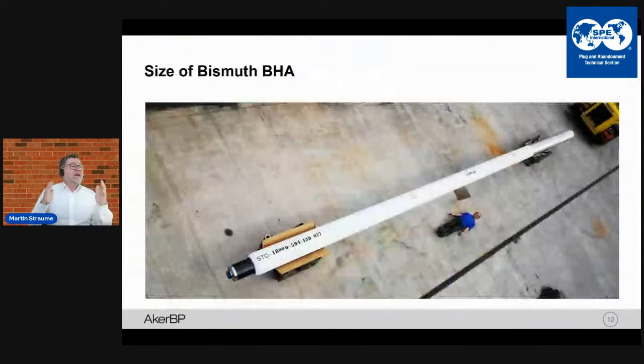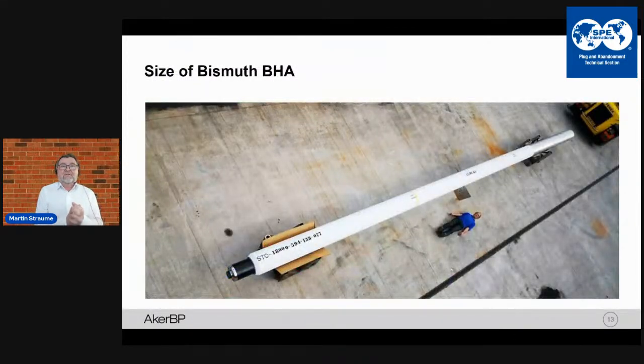So all the tests that we did was talking in the favor of bismuth material. So after we had a successful test, after we had removed this bismuth plug after 2 years in the field, we decided that, okay, we're going to go for bismuth plugs in all the wells in the shallow waters, basically 2 to 250 meters depth.